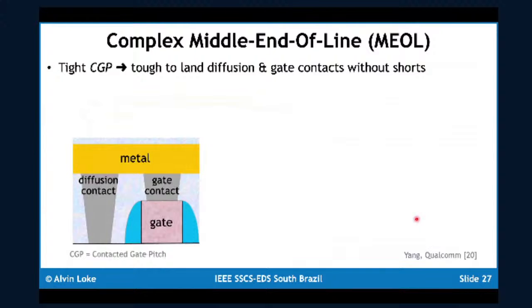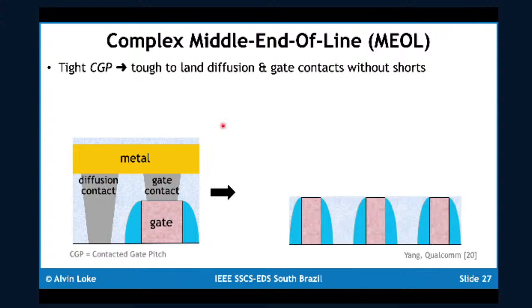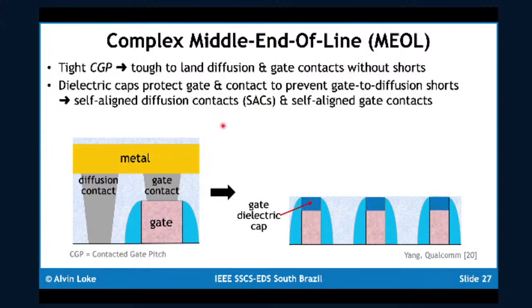The middle end of line is way more complex than these nodes. It's very difficult to land diffusion contacts and gate contacts. This is typically where all the yield problems are in a fab. Historically, in 28 nanometers, we had a single mask to do this. Well, guess what? As we've gone on to these more advanced nodes, we've had to incorporate the use of gate dielectric caps on top of the gate, such that when you have these self-aligned contacts that are misaligned, we don't short the contacts to the gate.